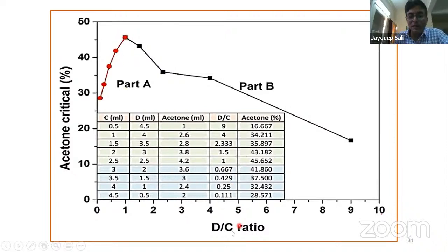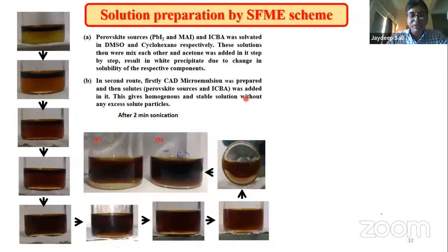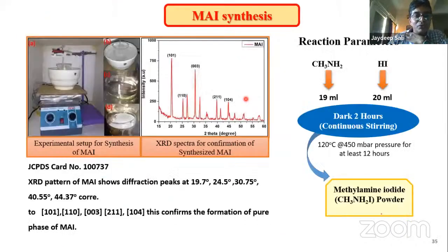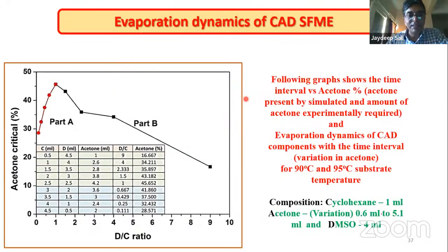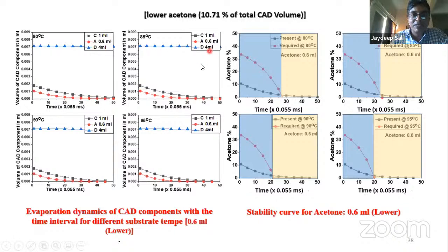Okay, so it means that as the proportion of DMSO and cyclohexane changes, we must have a specific acetone percentage to stabilize the microemulsion. If this specific acetone percentage is not present, then the microemulsion will become unstable and DMSO and cyclohexane, both these solvents, will form separate layers. Okay, so we use this fact to simulate the variation. See, now I will take 5 minutes to explain what we have done.